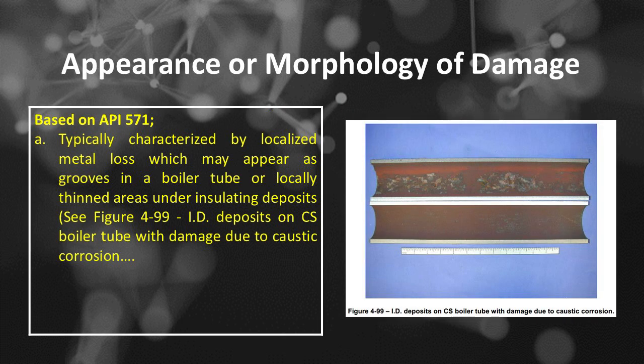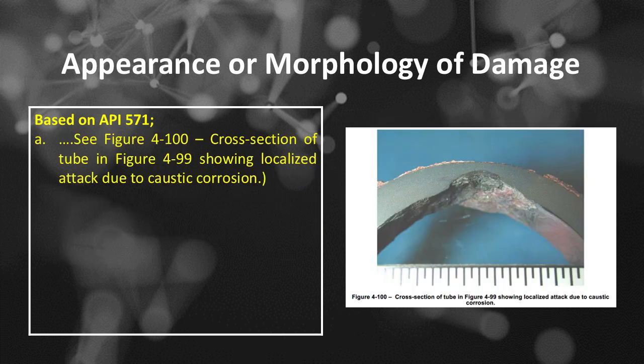Appearance or morphology of caustic corrosion damage based on API 571, Number A, typically characterized by localized metal loss which may appear as grooves in a boiler tube or locally thinned areas under insulating deposits. See Figure 4-99, ID deposits on CS boiler tube with damage due to caustic corrosion. See Figure 4-100, cross-section of tube in Figure 4-99 showing localized attack due to caustic corrosion.